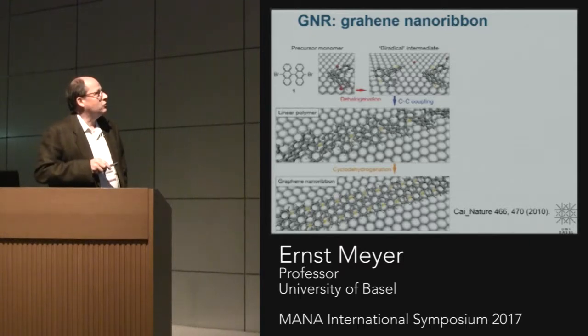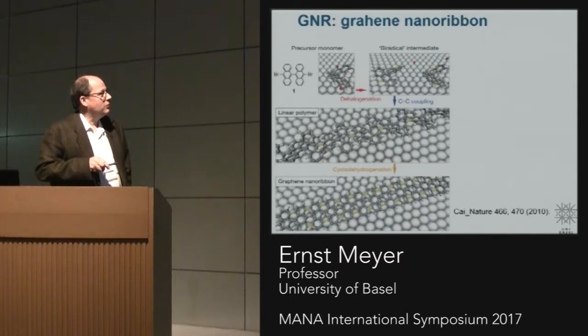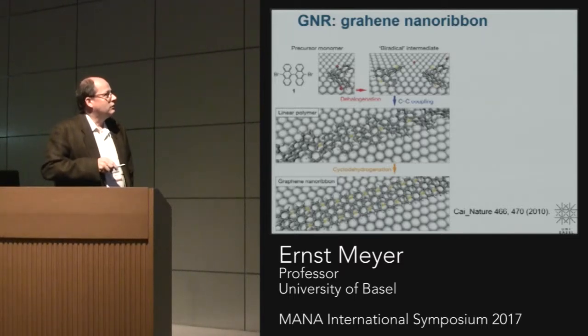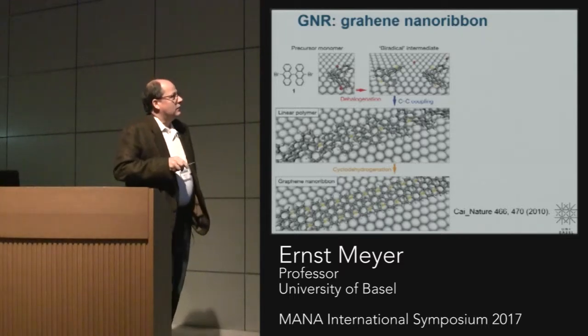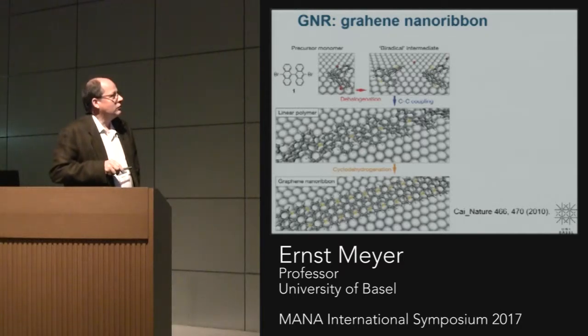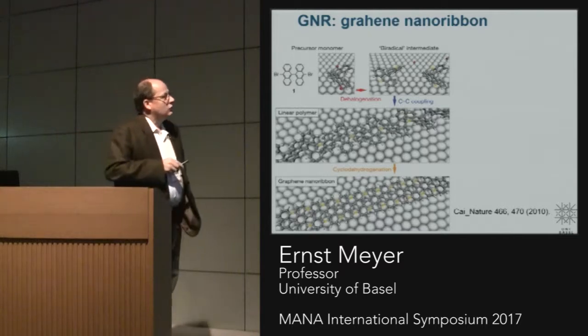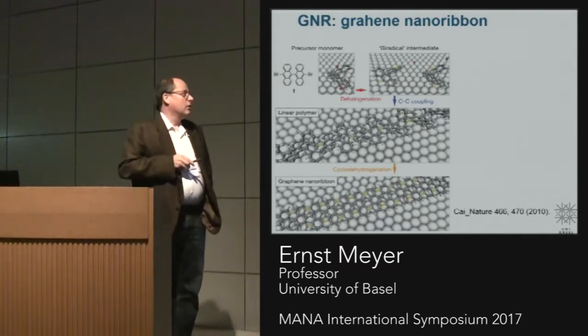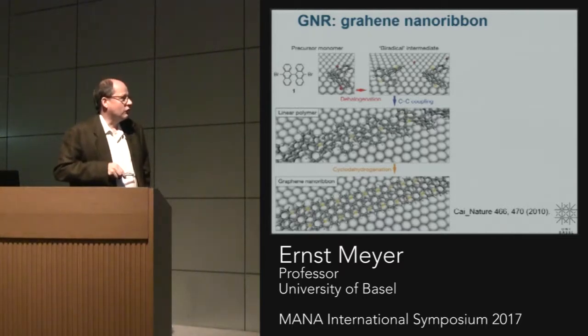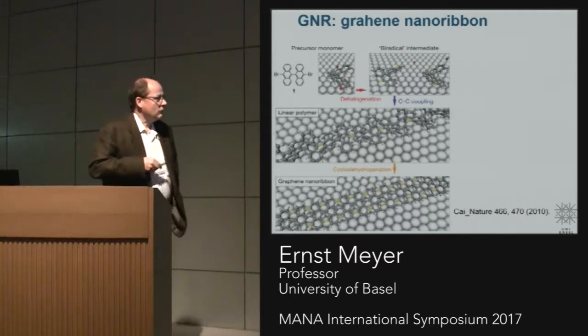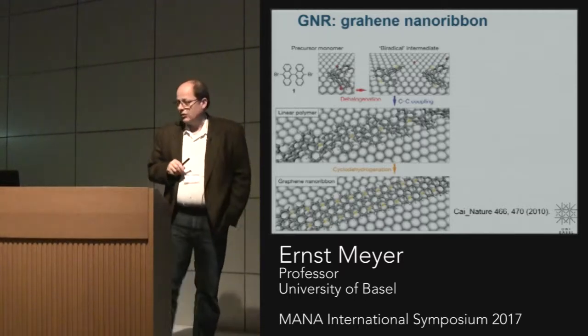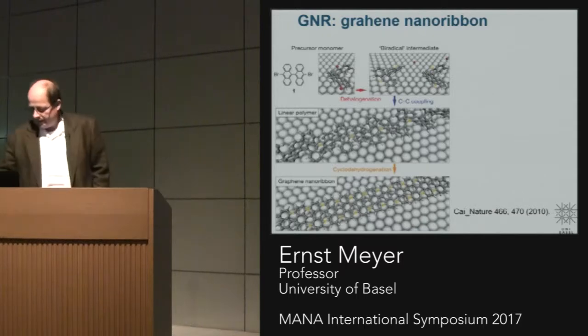So you start with a monomer, again with the bromine end groups, you heat it up, then bromine will diffuse away, and we have then the reaction here, forming first a linear polymer at around 200 C. If you further increase the temperature, you can form these nanoribbons, which, as you will see, turn out to be very nice and really only a few defects.